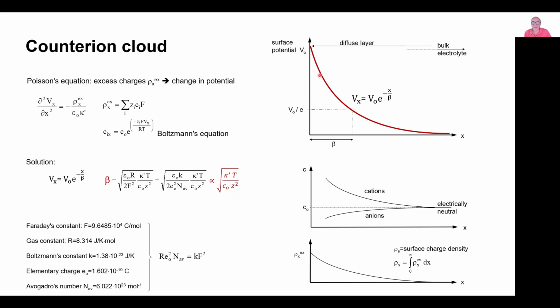So this thickness of the double layer, once again, realize that this is not a fixed number. It's the ratio of the potential decrease with respect to the origin by 1 over e. This thickness of the double layer is proportional to the permittivity of the pore fluid. Let's say 79, 80 if this was water, or 5, 6 if this was an organic fluid. The temperature, which will be in kelvins, by the time you plug into all these equations in order for them to make sense, the concentration in moles per liter, and the valence. Valence squared. This denominator is called the ionic strength.